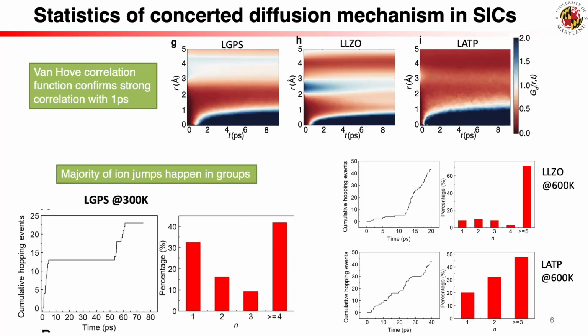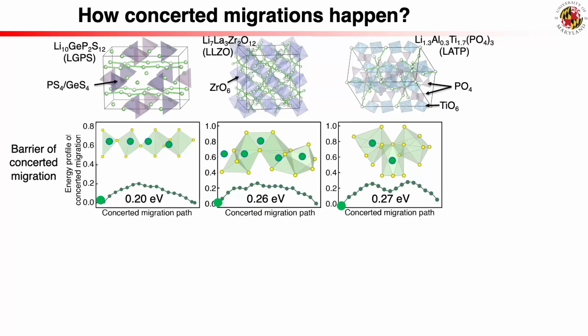These factors tell you how many ions are hopping together on average. They found a correlation factor of 3 for both LGPS and LLZO, and 2.1 for LATP. It means that roughly 2 to 3 ions are involved in a coordinated jump in these SiCs. So it's not just one ion at a time, it's a team effort. This concerted migration, which we usually think of in liquids, is actually the main way ions move in these solid super-ionic conductors. It's a paradigm shift.